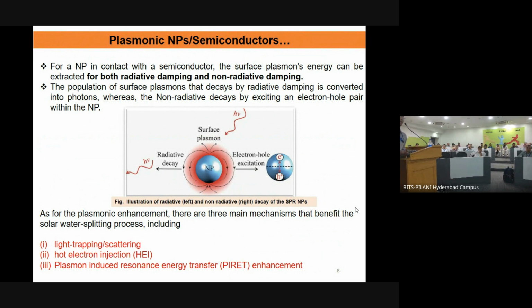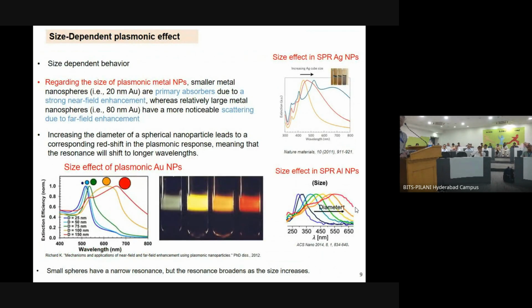Whereas if the particle size is suitable enough, you can think of hot electron injection, or it can also lead to plasmon induced resonance energy transfer, which is like a PIRET kind of a thing. So this is, you look at that, the same gold, especially noble metal based. The small particles like quantum dots or plasmonic nanoparticles are well studied. If you look here, the light absorption cross section, in the sense the lambda max, is pushed with increasing size, you see there is a redshift which is happening. So now you see that the absorption cross section also increases.